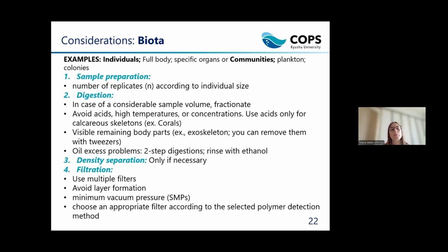And it can also happen that you have some oil excess problems in your samples from some fatty fish or something like that. In that case, I recommend to use two-step digestions or maybe enzymatic digestion using a lipase enzyme, or also a good technique is to rinse your filters with ethanol to remove some of the oily excess.